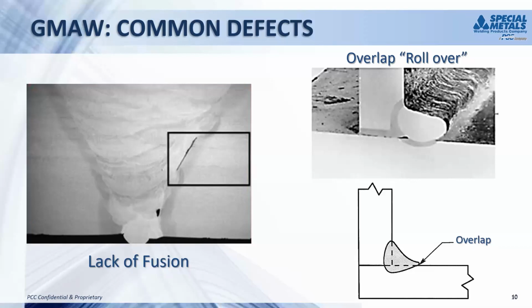But the other challenge, if you go too slow with the MIG weld, one of the very common defects that comes up is something called overlap, or typically referred to as rollover. If you look at the weld picture on the right, basically what happened is they were going just a little bit too slow, and that very sluggish metal just rolled over, and it sat on top of the base metal and didn't really burn in. It gives you potentially lack of fusion. And then as you come in with your next pass with the lower penetration of a nickel weld, you just don't burn into that previous bead and don't really penetrate in and get rid of those problems.